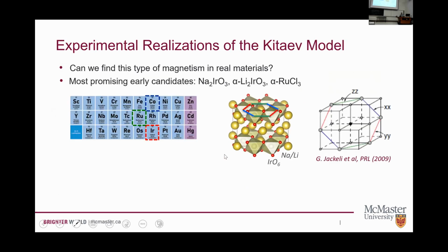Okay. So we have this picture where in materials with strong spin orbit coupling, we get J-effective moments. And if we put them on a honeycomb lattice, there's a chance that we can get these Kitaev interactions. As long as we've got these 90-degree bonds that we should find for edge sharing geometries, then in theory, these Kitaev interactions can emerge. But just because they can emerge doesn't mean that we can actually see them. So the first thing we wanted to do was to look around to see if we could find evidence of this Kitaev physics in real materials.